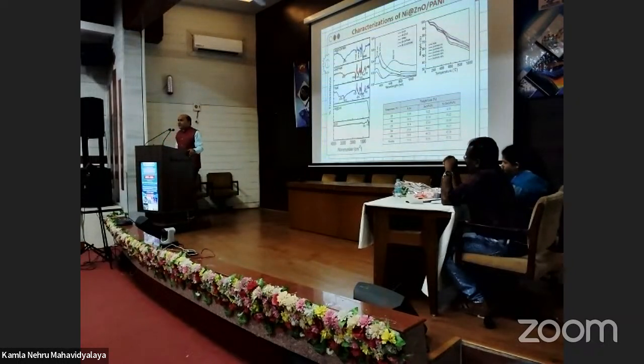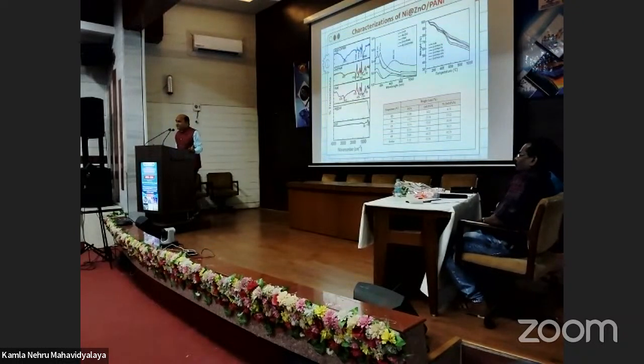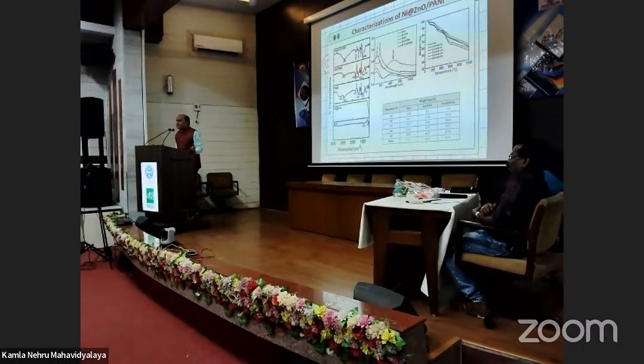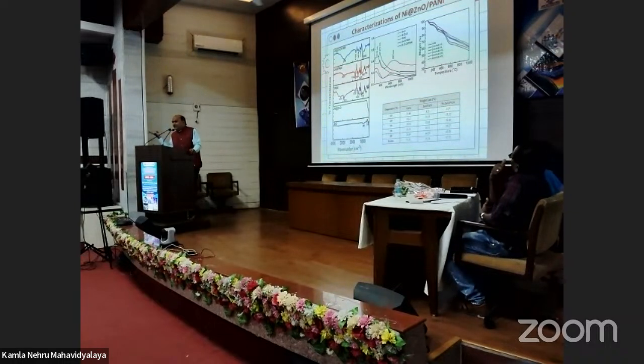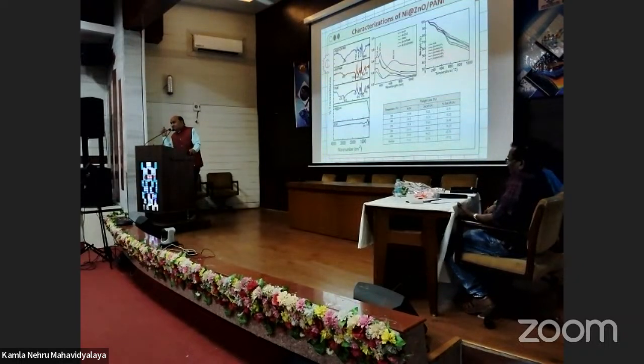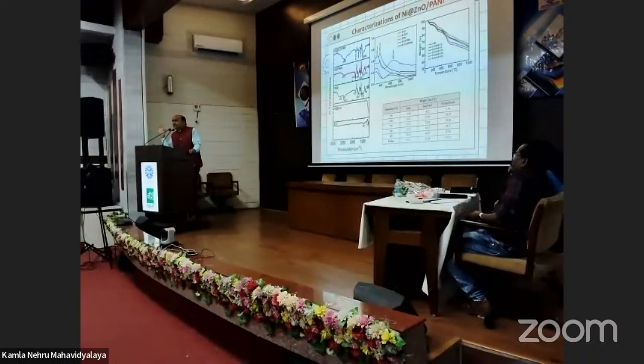Then we have done UV DRS, that is diffuse reflectance UV spectroscopy for the solid material, and then we tested its thermal stability also. The values are put here in the table: weight loss in percent, initial decomposition temperature, mid decomposition temperature, and final decomposition temperature. The initial and final decomposition temperatures are very important. Initially the material starts to decompose, and finally it is completely decomposed, with formation of ash content. When a material takes more time to decompose, it is considered thermally more stable.